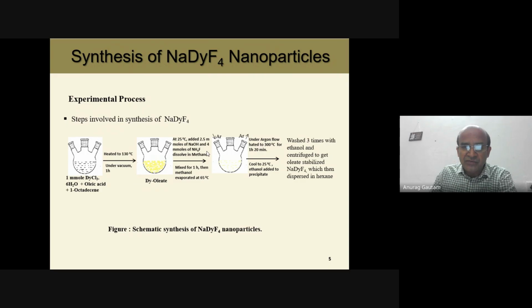Add sodium hydroxide and ammonium fluoride in methanol solution, and mix for 1 hour. Sometimes you can go for a longer duration, 2-3 hours, it doesn't matter, because this is at room temperature. Then you have to heat it with argon flow from one side, because we have to work in an inert atmosphere. This is a Schlenk line setup. We connect it with the tube, and argon comes from one side and goes out the other. Once it is heated to 300 degrees centigrade with an oil bath, that will give the sodium dysprosium fluoride nanoparticle, and dysprosium is a T2 contrast agent. Then we wash 3-4 times and centrifuge, and you'll get this nanoparticle.